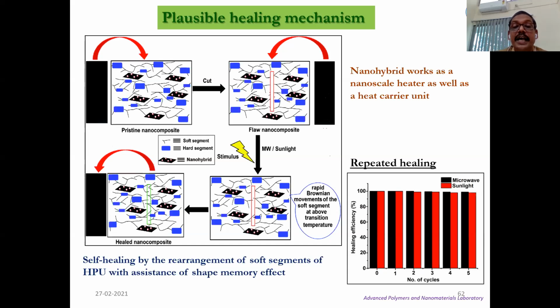And we have described that this nanomaterial acts as a nano heater. When this microwave or sunlight is exposed to the matrix, they absorb this energy and dissipate it to the matrix, and matrix temperature is increased above the glass transition temperature, and thus Brownian motion of the soft segment starts, which results in healing of the damaged surface. And efficiency, if you see, is even after the fifth cycle, almost 100%. Thus, you can get self-healing character repeatedly.